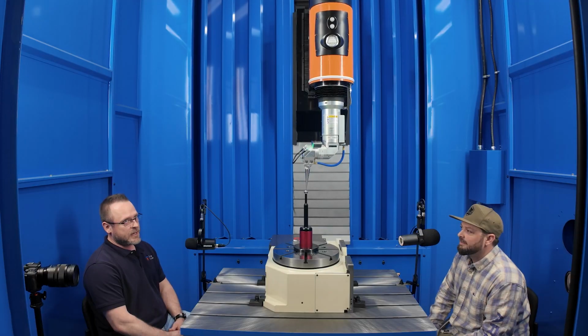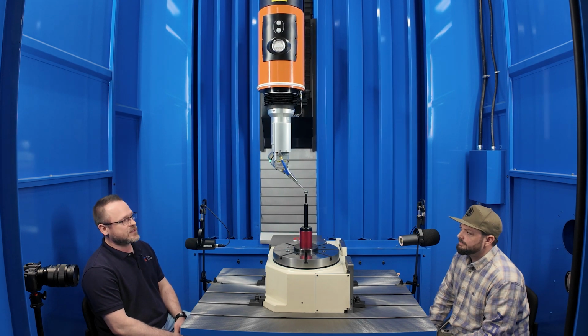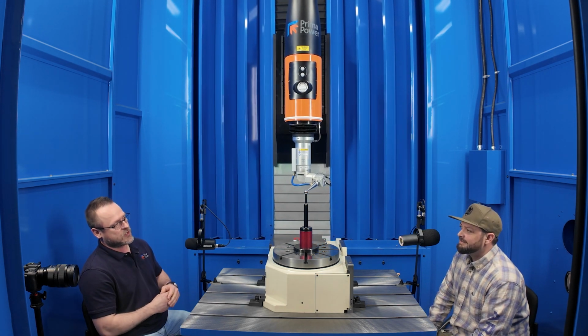That's a big thing. As far as the welding that we've seen here, it's mainly autogenous welding, no wire. So that's the main thing you do. Most of the welds, how big are the welds you're working with? Kind of depends. We can have anywhere from probably a 32nd of an inch or a 16th of an inch wide. I think you might have saw some of those, very, very thin conduction welds. You can also get very thin keyhole welds, but it can really range. It just depends on the application and the desired outcome that people have for the parts, whether you want full penetration, more of a cosmetic weld. It can really vary, and we can do a lot.